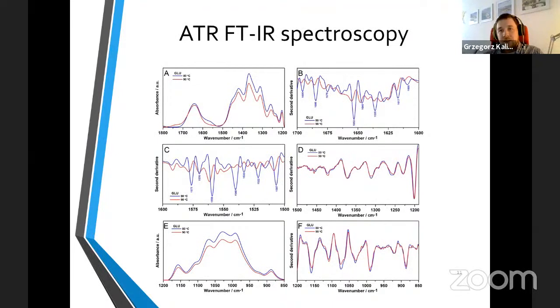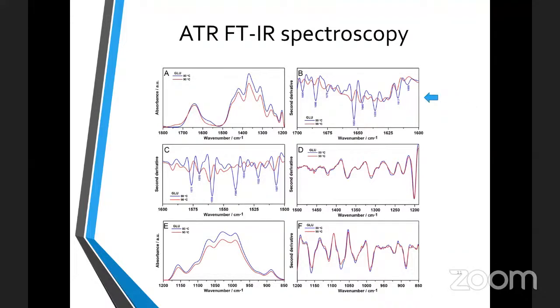So it showed similar pattern for both samples, but second derivative in planes B and C revealed many additional bands in 80 degrees sample comparing to 90 degrees sample. They were assigned to changes in secondary structure. No other changes were observed, as you can see in spectra and second derivatives in planes D, E, and F. So here are the most important changes.